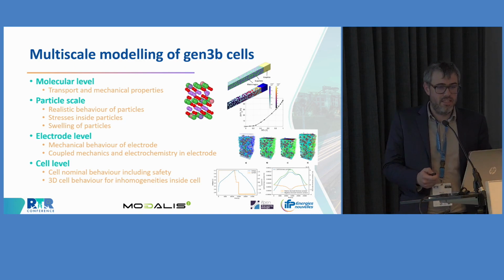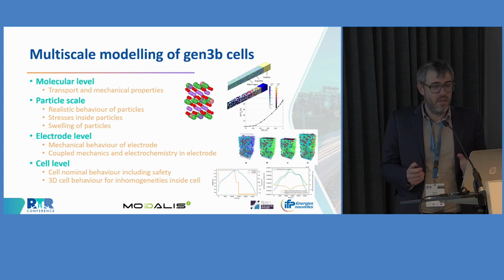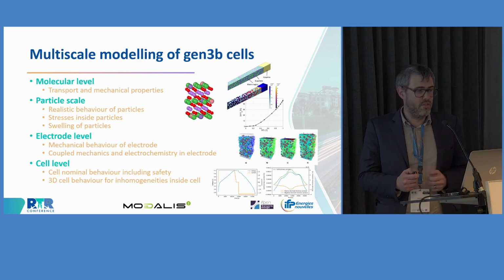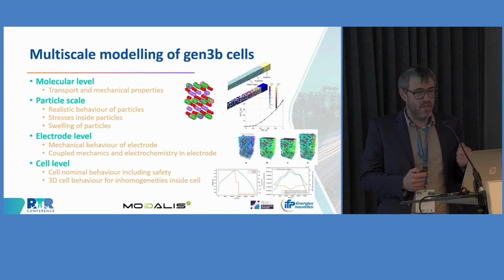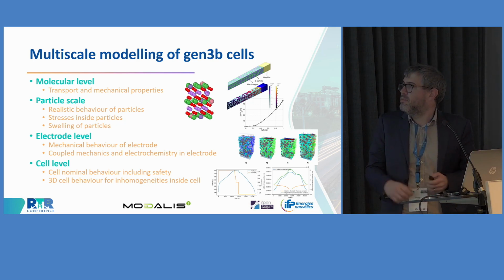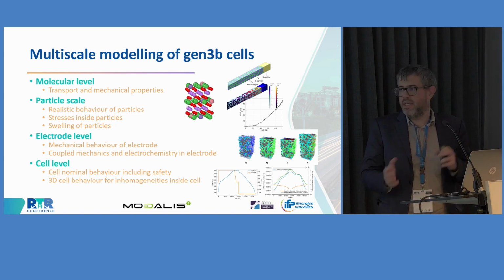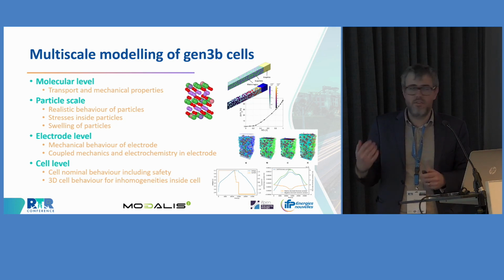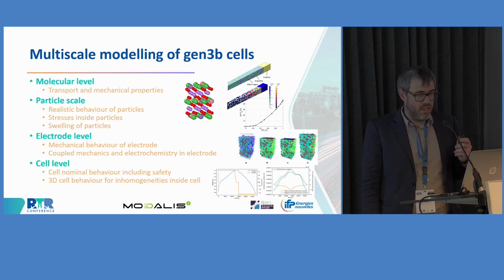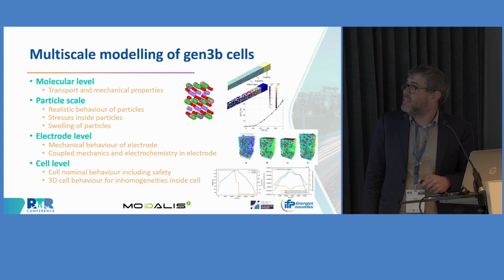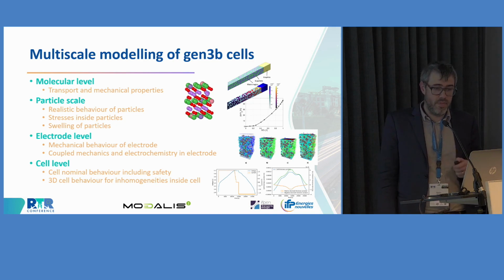So the modeling, as I said, was done at multiple scales. First, at the molecular level, we are able to get the transport and mechanical properties of the materials, especially for the NMC, the diffusion parameters of the NMC, and the mechanical properties of the silicon. Because we bought some commercial material with silicon coupled with graphite, it was not possible for us to separate silicon and graphite and analyze them separately. So we had to guess the material behavior from DFT calculations.